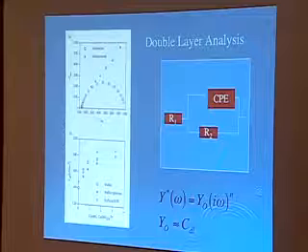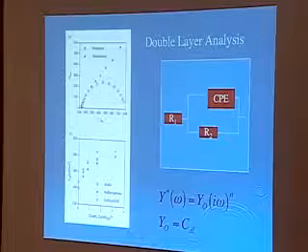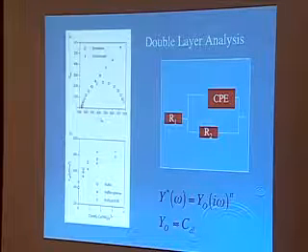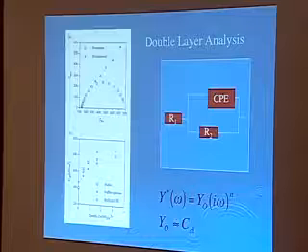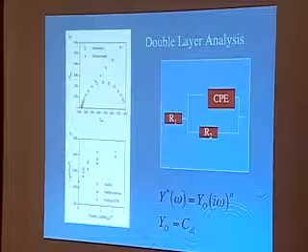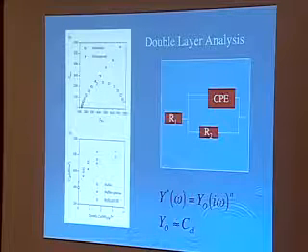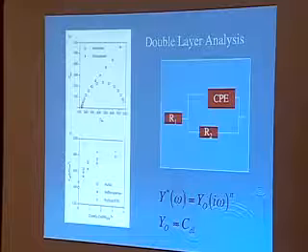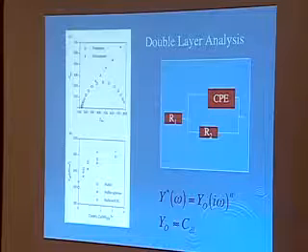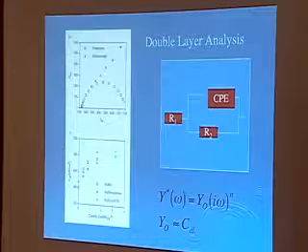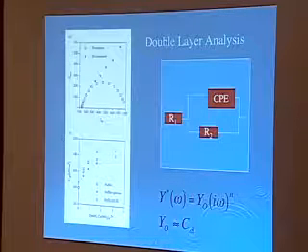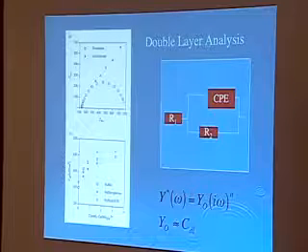It's the diamonds. And the first reason I show this to you is that's not atypical of what real-life AC impedance data looks like. That is, the stuff I showed you on Tuesday was a little too good. So it wasn't perfect either. But the idea is you expect there to be a semicircle, so you fit it to the best semicircle you have. So that's the semicircle fit to this data. Okay. And you do it under circumstances where you just have the derivatized electrode and buffer, and you have buffer plus glucose in there with the derivatized electrode, and you have buffer plus glucose oxidase plus glucose in there. And you do all of those, and you find it doesn't matter that much which you do.